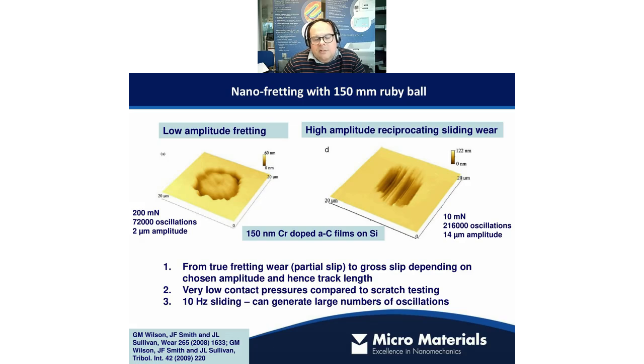So this is another example where we've looked at a thin amorphous carbon coating on a silicon wafer, so it's a 150 nanometer thick layer. And we've done fretting tests at two different amplitude scales. So at the low amplitude, we're talking about a 2 micron oscillation, and we're using 200 millinewtons to apply this. This should say micron. I don't know why this has got changed here. It's a 150 micron radius ball.